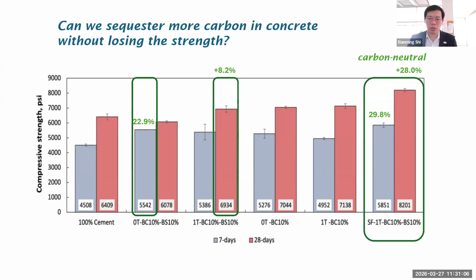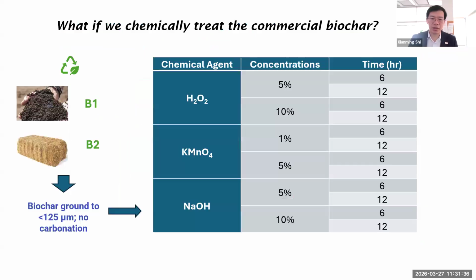Now, if we want to achieve carbon neutral concrete, here's a very interesting mix design. Of course, we had to rely on 10% silica fume to replace the cement binder, and then we used 10% of the engineered biochar to replace cement, and then 10% of coarse biochar to replace sand. And you can see, compared with the control, we're achieving roughly 28 to 30% better strength, both at 7-day and 28 days.